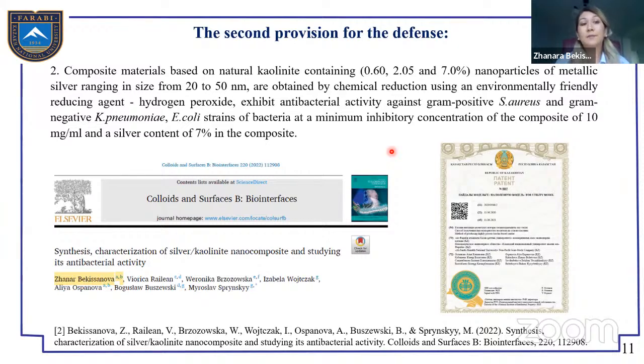And this is the second provision for defense: composite materials based on natural kaolinite containing 0.6, 2.05, and 7% of nanoparticles with size from 20 to 50 nanometers are obtained by chemical reduction using the environmentally friendly reducing agent hydrogen peroxide, and can exhibit antibacterial activity against gram-positive Staphylococcus aureus and gram-negative Klebsiella pneumoniae and Escherichia coli, with minimum inhibitory concentration 10 mg per milliliter and silver content of 7% in the composite. This provision was published in the article in Colloids and Surfaces B: Biointerfaces and is supported by the following results.